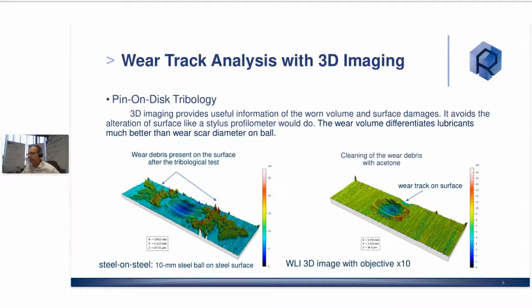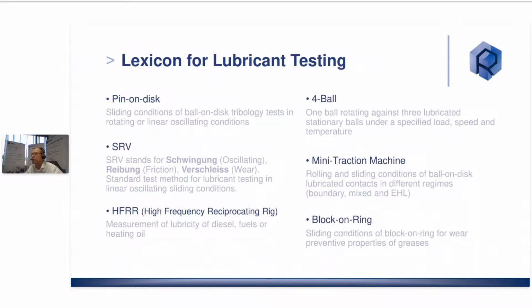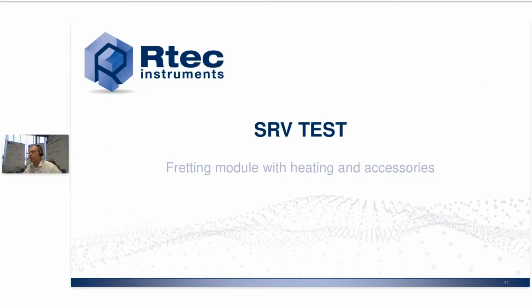We can have a very nice image about presence of particles, complete wear volume evaluation on the surface of the material. When we are going into lubricant testing, there are specific modes of testing that are generally related to ASTM and ISO standards. Pin-on-disc tribometer, which is sliding condition of ball on disc, is a tribological test which is really well known in the field of tribology, but there are other testing methods extremely important for lubricant testing. Going from the SRV test method, HFRR test method for lubricity of diesel and fuel, the 4-ball testing, the mini traction machine, which has been growing interest in our application, also related to electrical contact resistance and impedance measurements, and for some applications as well, the block-on-ring test.